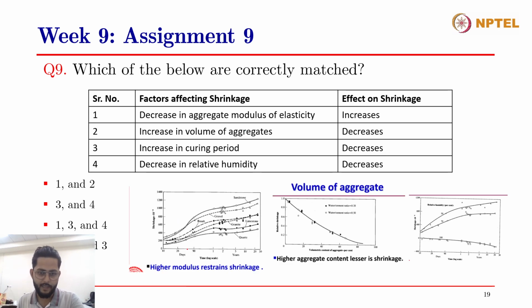Again, coming back to shrinkage, when you decrease the aggregates modulus of elasticity, here I have taken a view graph on this slide, and you can see that this is the shrinkage, and these are the different types of aggregates, and they have shown that when the modulus of elasticity of aggregates increases, the shrinkage gets reduced. So you can see that granite, which has a higher modulus of elasticity, has a lower shrinkage than sandstone per se. So as you increase the modulus of elasticity of aggregates, the shrinkage decreases. So the first one is correct.